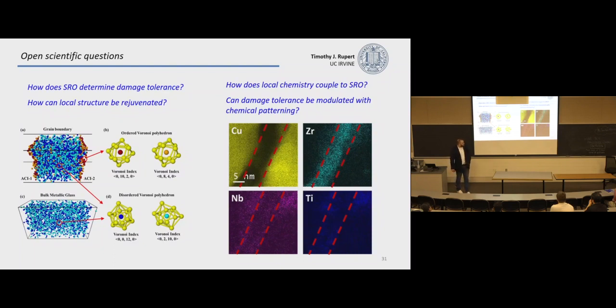And we also are trying to poke at how we can control that in a meaningful way. One way we're trying to do it is by looking at how you get interesting patterning of different elements at the grain boundary. So this is showing a grain boundary in copper, zirconium, niobium, titanium. I said all those things go to the grain boundary, but it turns out they don't all go to the grain boundary evenly. So this interior region, which is more disordered, ends up being more heavily doped with zirconium. It's always hard to see with lights and things, but these regions here are marking those amorphous crystalline interfaces, and they're more heavily doped with niobium and titanium.